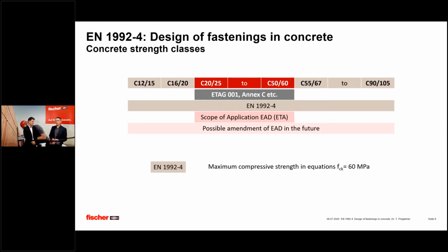In terms of functionality of the products, the high strength part is more challenging, because you must make sure that, for example, friction-based systems are still working in the, let's say, relatively smooth and straight drill holes, which is the challenging part. In terms of design, it is restricted in any case until now, because the current equations for concrete-related failure modes are restricted to a maximum compressive strength of 60 megapascal. That means even if the product is qualified in a C90, still the limit for the maximum concrete cone performance is limited by a concrete strength of 60 megapascal. Okay.